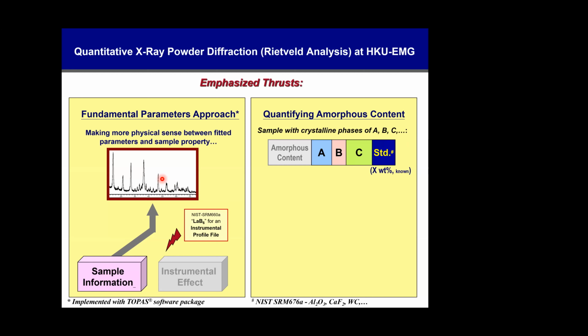Another thing is a lot of people have been troubled by XRD because XRD cannot see amorphous. It's very natural, because if you don't have a crystal, XRD cannot see it. And if we look at our natural materials, who says that you don't have amorphous content? You might actually have quite a lot of amorphous content right there, and you are taking it for an experiment and you only explain your result by the crystallized parts. You're missing too much on something that you are not seeing. So you have to quantify the amorphous content.